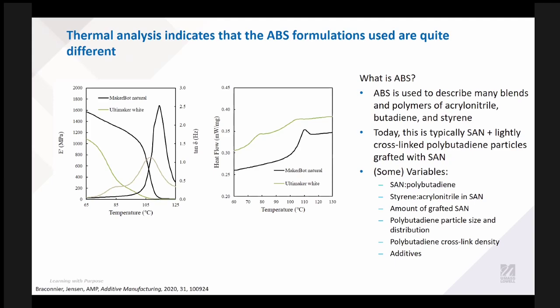One of the things that we learned pretty early on was that even though we had tried to acquire ABS that was as similar as possible for the printers, we needed to have 2 spools of filament, because we had printers that used different diameter filaments. And so we ended up getting the non-colored versions and getting relatively high quality versions. But from here we can see in DMA and also in DSC that these materials are very different from each other. One of them exhibits 2 Tgs. One's got a very clear single Tg. Yeah, they're very different materials.